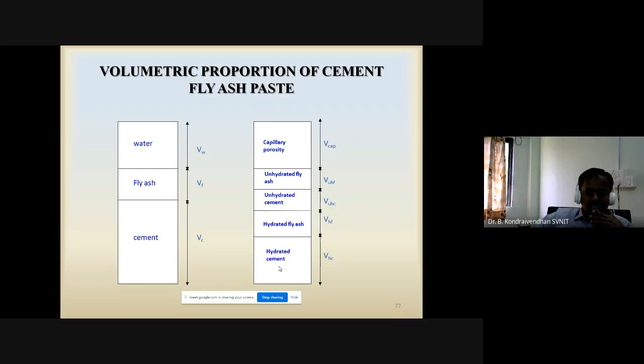So if you look at the cement fly ash system, what is the volume proportion? We are using cement and fly ash and water. This is our original volumes. VC is the volume of cement, VF is the volume of fly ash, and VW is the volume of water. If you mix all the things together, what will happen? What end products will you get? You will get hydration of the cement, hydration of the fly ash, and some unhydrated cement and unhydrated fly ash will be there.